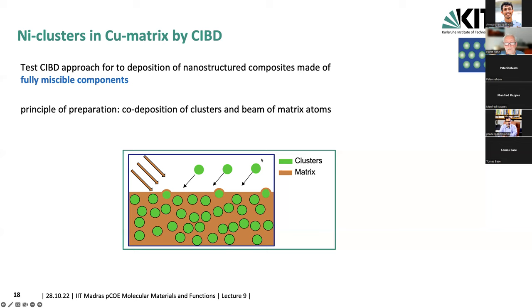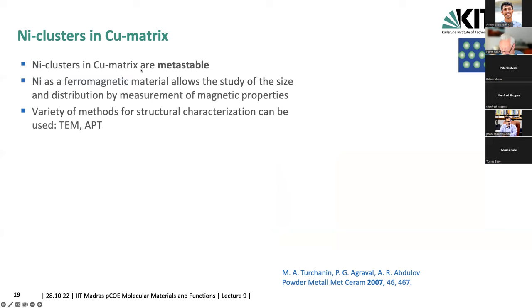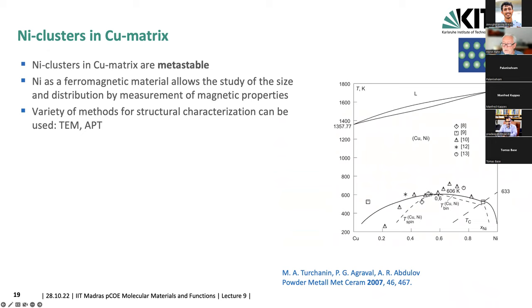So nickel clusters in copper would be metastable, because here is a phase diagram, and you see it's a fully miscible system. There is some indication which people have reported of a spinodal decomposition at very low temperatures. This cannot really be achieved by thermal treatment anymore because the temperature is too low, so diffusivity is small. So people have done that under an irradiation environment, where you create radiation-enhanced defects in order to get the atoms to move. But this is outside the range of our compositions.